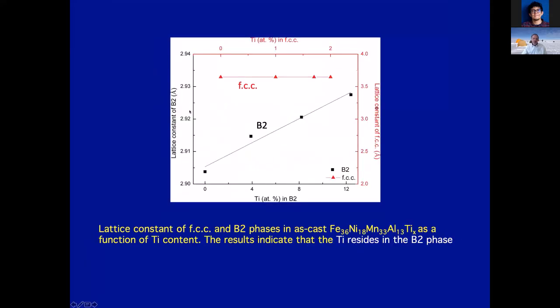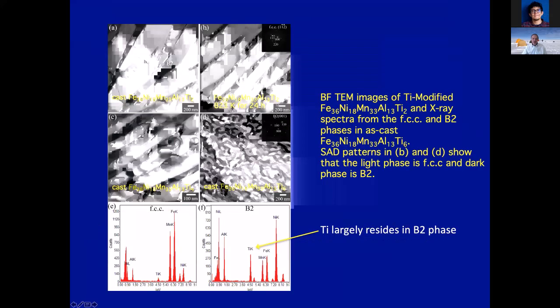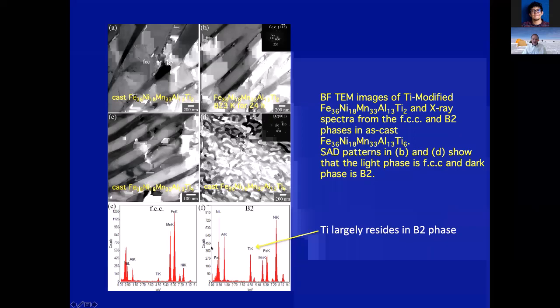And if we look at what happens to the lattice parameter as a function of titanium, what you see, interestingly, is that the FCC lattice parameter doesn't change, but the B2 lattice parameter increases linearly with increasing titanium, which suggests that the titanium largely goes into the B2 phase of the material. And when we look in the TEM here at the chemistry of the FCC phase and the B2, you can see the titanium is largely in the B2, and there's very little in the FCC phase in the material.